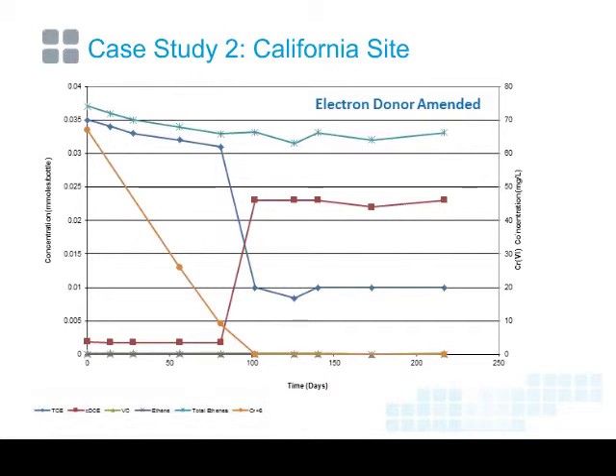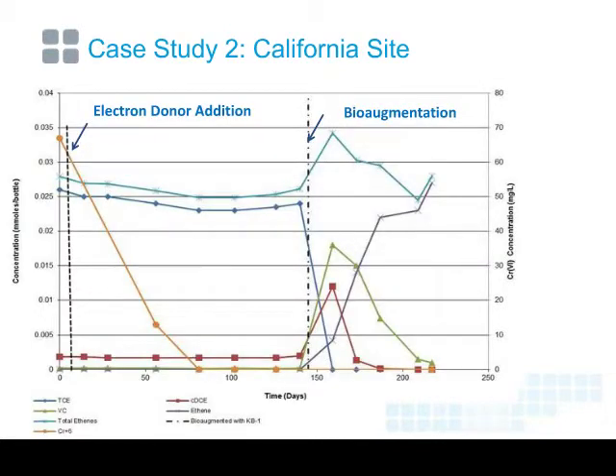And so when we now look at our bioaugmented treatments, it's exactly the same as the previous treatment with the exception that it was bioaugmented just before day 150. And you can see the same results as before. Initially, hexavalent chromium dropped out. We didn't actually see the TCE go away at all in this treatment. Once we bioaugmented, then we saw cis-DCE and vinyl chloride being produced, with the production ultimately of ethene, and a good mass conversion of all the moles of TCE were converted to ethene, which is very typical for chlorinated ethene bioremediation sites.